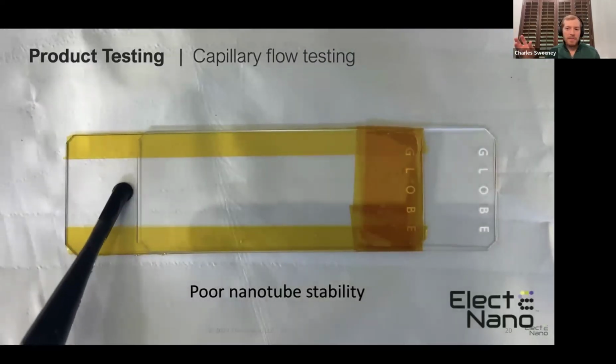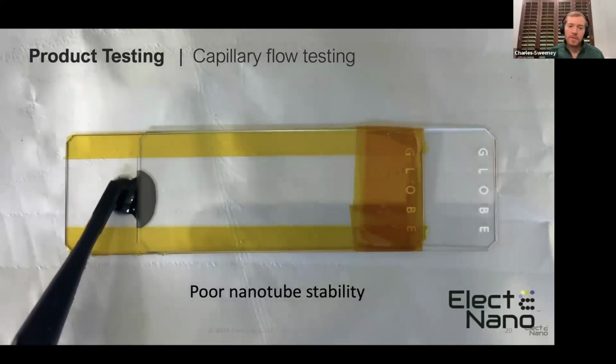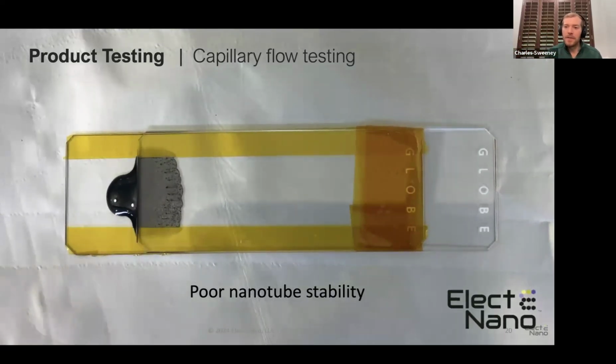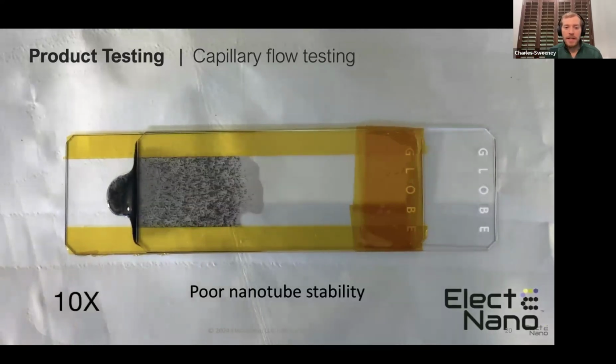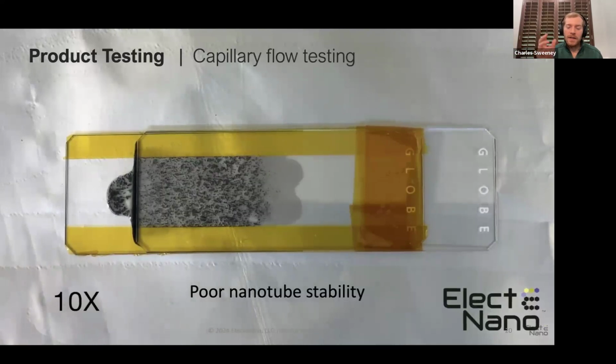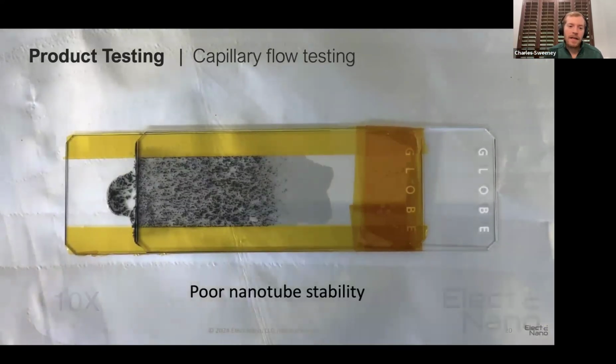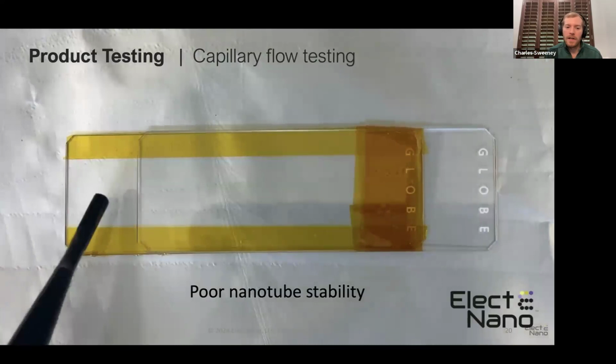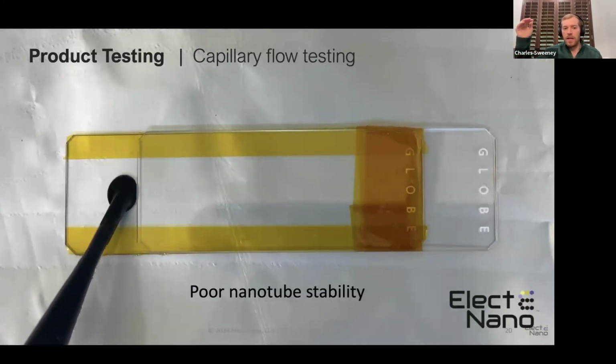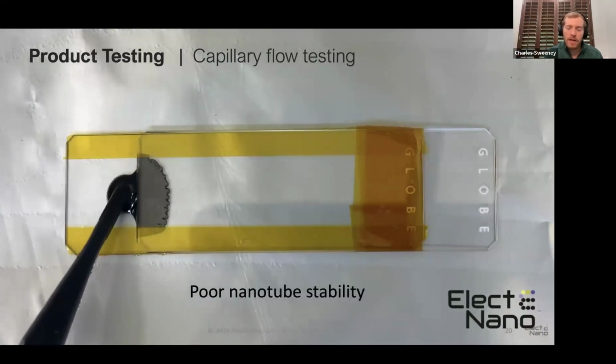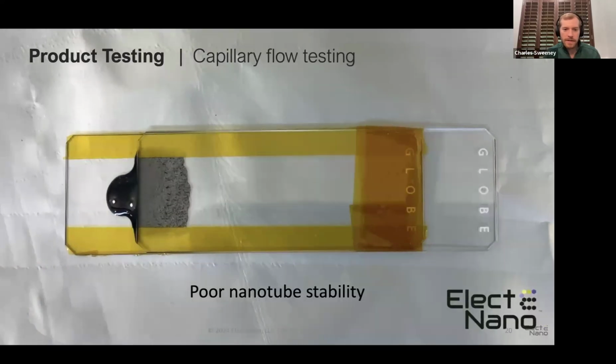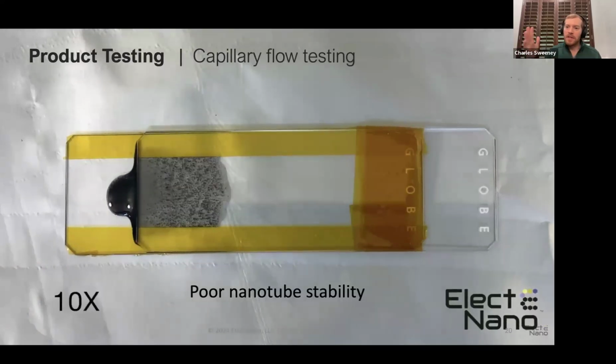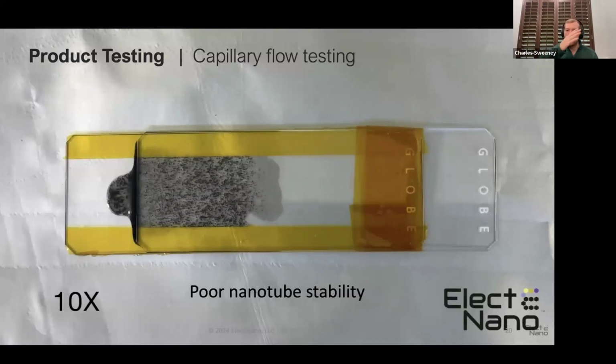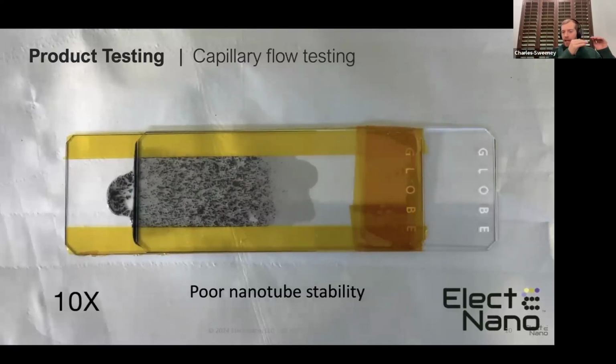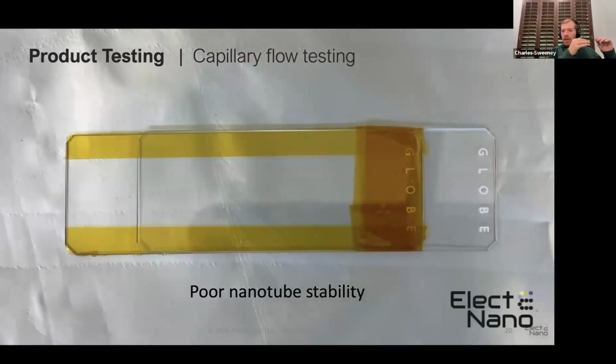If you just take carbon nanotubes, even discrete nanotubes, and you just try to sonicate or blend them into one of these underfill components at room temperature, it may look like you've got a good dispersion. But these are usually dispensed and cured between 100 and 120 degrees Celsius, and then cured to their final Tg around 160 or 170 degrees Celsius. The surface chemistry is changing dramatically throughout that thermal processing. You can't just engineer for stability at room temperature.